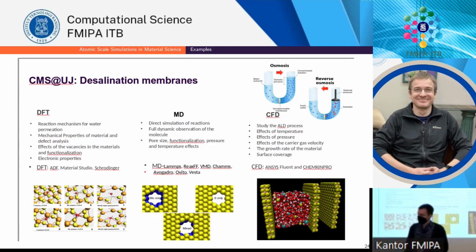Now, the tricky part is that if we do this with molecular dynamics, in this case with LAMMPS, the interaction between the ions and the molybdenum disulfide is most likely not going to be represented properly. So we have to double check with DFT, atomistic simulations on the very left, to see what is actually the interaction of different ions we find in the water with the surface of the MoS2, because we don't want things to happen like the ions getting attached to the surface. We don't want any chemical reactions happening there, right? So we need different methods of different scales to cover all the different processes. So this is basically the minimal setup of a multi-scale model, right? In a very crude fashion.